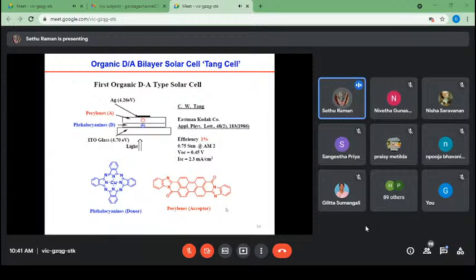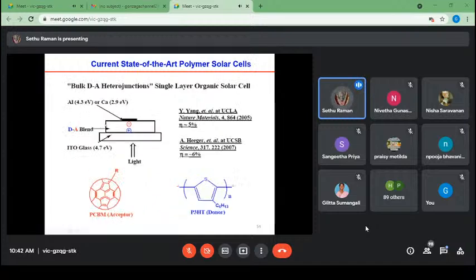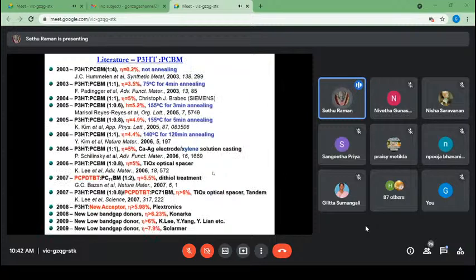Both are small molecule semiconductors. Both layers are prepared by thermal evaporation technique under high vacuum condition. Then the bulk heterojunction was prepared by the Yang group as well as the Alan Heeger group. They published papers in 2007 and 2005 using an acceptor small molecule, mixing the two to prepare a donor-acceptor blend, and then preparing the thin layer between the two electrodes. In this work, they achieved power conversion efficiencies of 5 and 6%. So these are some of the literature I put here.